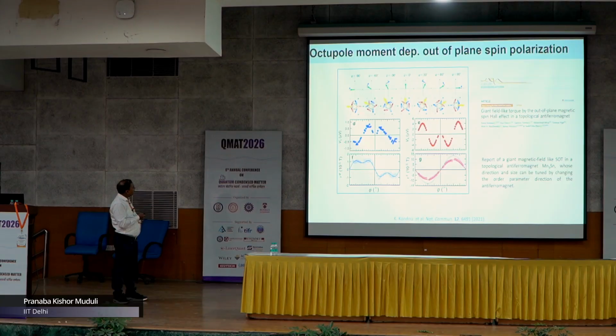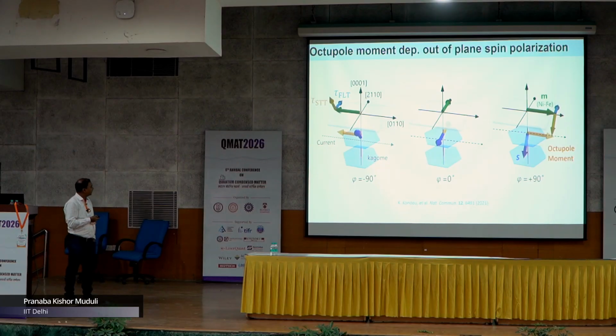What they showed is that as you change this octopole orientation, you can change the torque acting on the magnetic layer. There they also have a structure of Mn3Ir and permalloy. So they are able to change the torque by changing this octopole moment. This can be understood more clearly from this figure here.